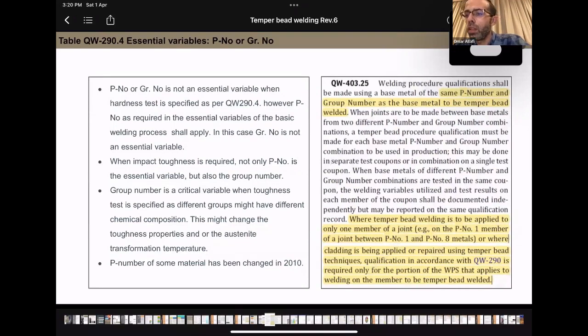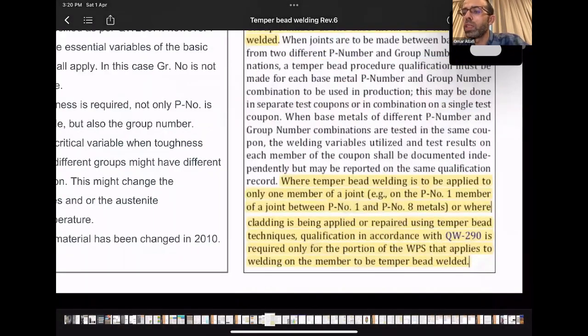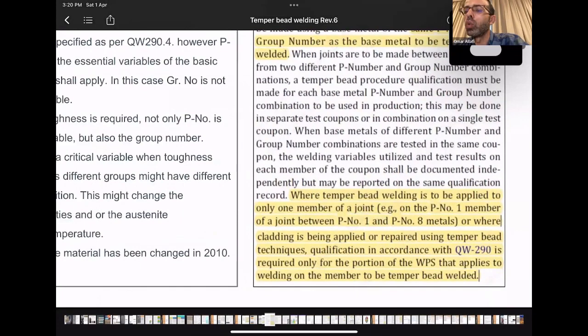And another point here, where temper bead welding is to be applied to only one member of a joint, like in case of cladding, like when you have a dissimilar weld joint, like carbon steel to stainless steel, and you apply buttering of 309 on the carbon steel side, and this requires PWHT as per the specification. So you can use the temper bead for this part of welding only, for buttering 309 filler to the carbon steel, and the subsequent welding will be done normally without temper bead.